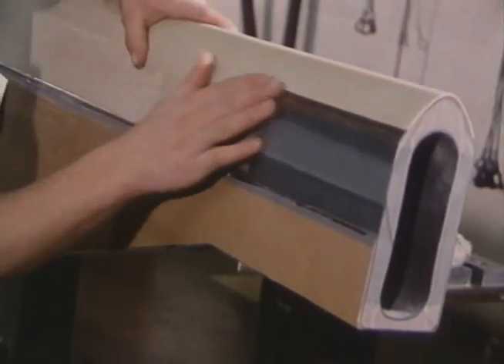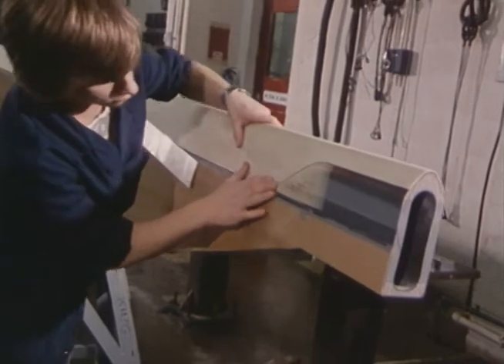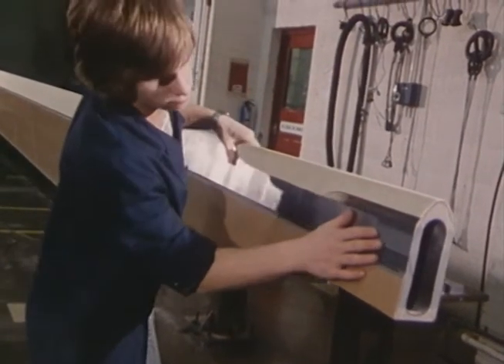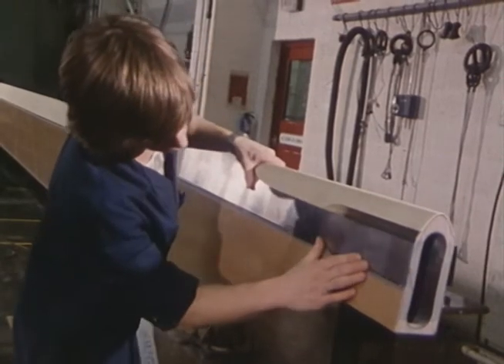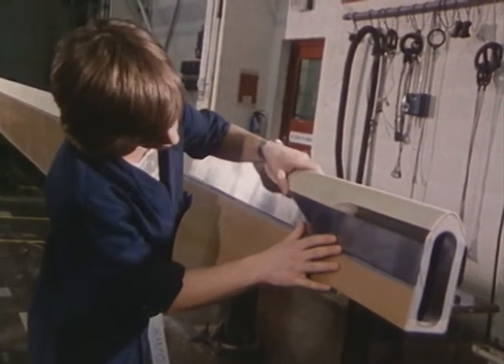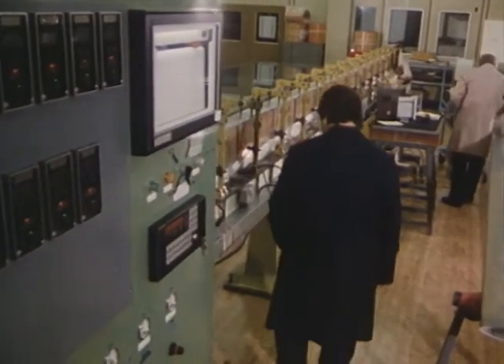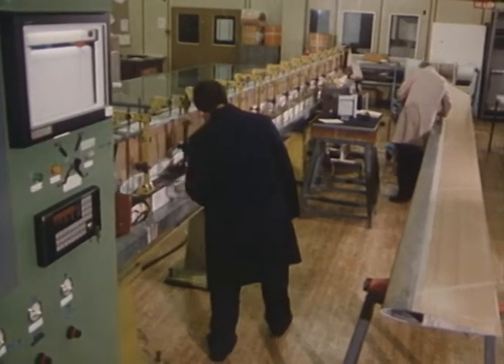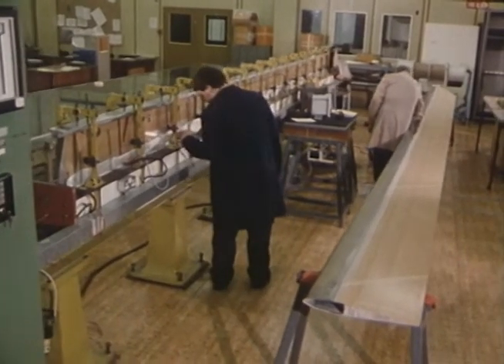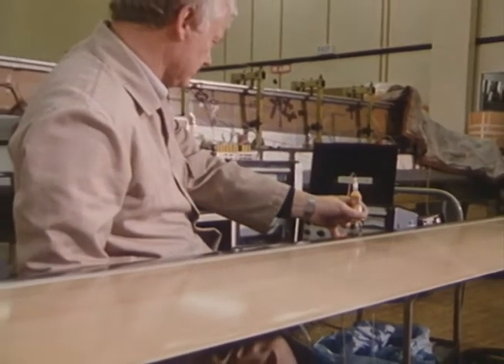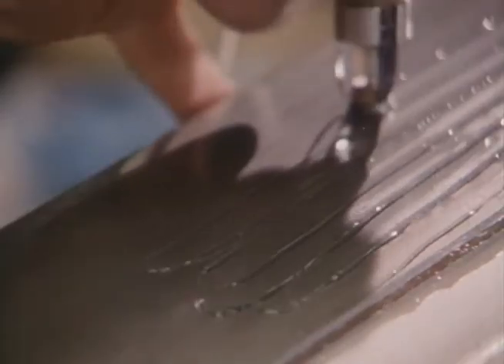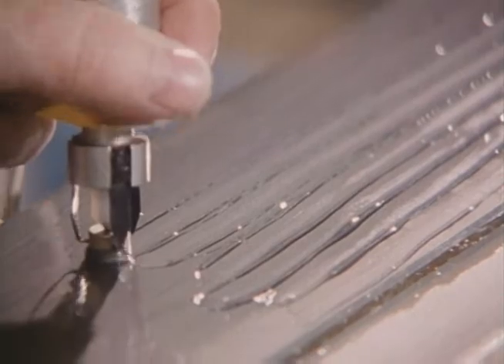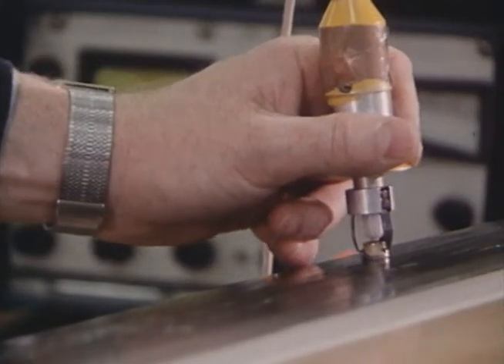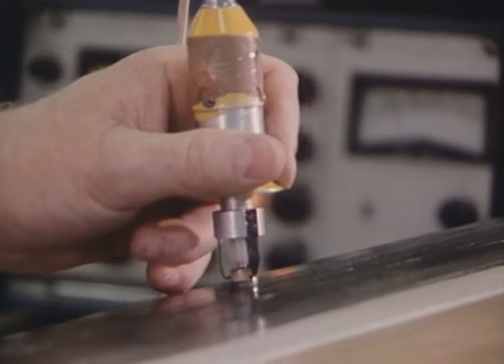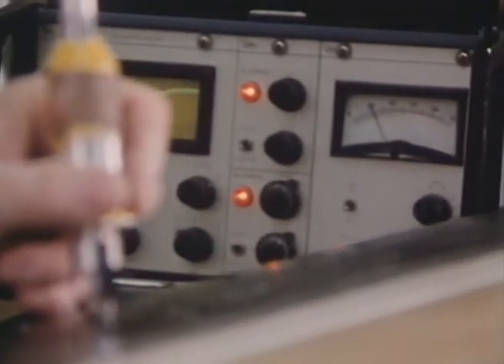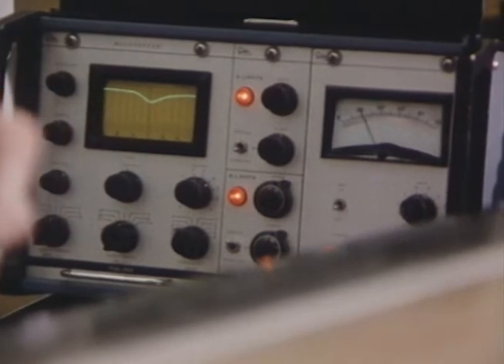After this inspection, the leading edge erosion shield assembly is bonded to the spar. These 4 replaceable titanium sections protect the composite spar from erosion damage and give a conductive path for lightning strikes. The erosion shield assembly is bonded to the blade in a microprocessor-controlled rig. When cured, the bond is checked by thermography or, as here, by an ultrasonic signal passing through a transfer gel. The presence of a void or D-bond changes the signal sufficiently to detect the defect. Our confidence in the integrity of bonded joints is based on this extensive and detailed inspection.